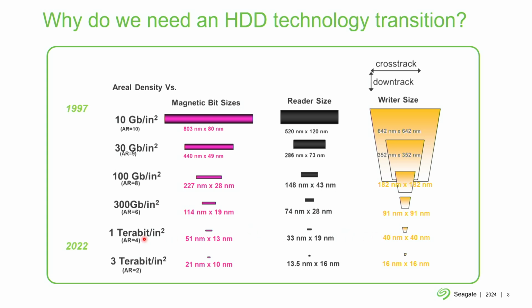And yes, it is the physical dimensions of these devices that have led to these drastic increases in areal density, but also the technologies are fundamentally changing over time. Around the year 2000, we went from longitudinal magnetic recording to perpendicular. Longitudinal magnetic recording means that the magnetization of the media was in plane, as opposed to perpendicular, where it was out of plane. So that led to a significant increase in areal density. Sometime after the year 2000, we went from giant magnetoresistive sensors to tunneling magnetoresistive sensors. And many years before that, they were inductive.